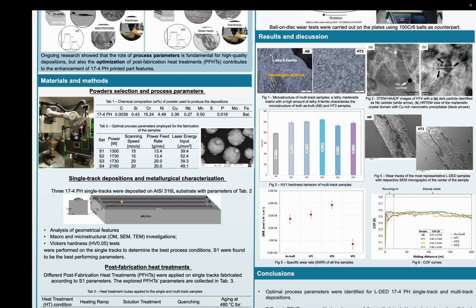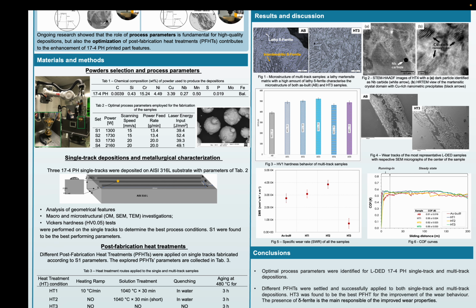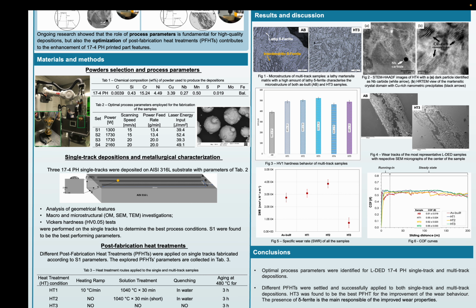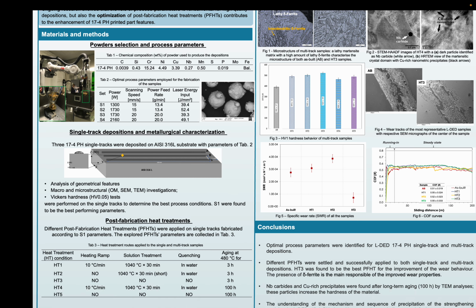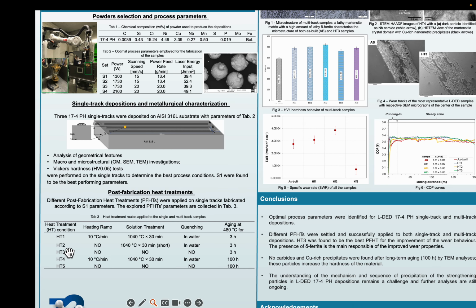With a preliminary study, different sets of process parameters, including power, scanning speed, powder feed rate, and the calculation of laser energy input, were selected in order to fabricate the present specimens. Three replicas of each single track using the different process parameters were deposited on an AISI 316L substrate, as we can observe in the figure, which were further studied in terms of geometrical features, macro and microstructure through optical microscope, scanning electron microscope, TEM, and microhardness analysis.